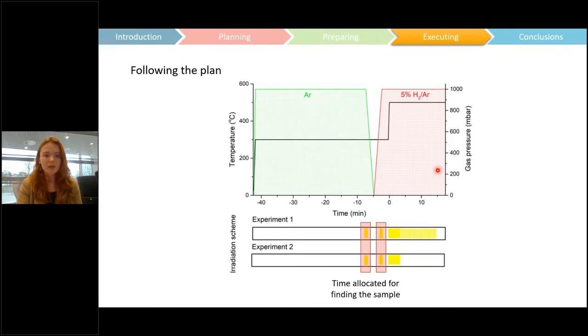And then it's just as simple as following your plan because you have a plan, you've come in with your diagram, you know what you're going to do. You have your time allocated for finding the sample. So you run your drying step. I know it's so tempting the second you get the holder in the microscope to switch the beam on and see your sample, but really hold off, run that drying step, run, I don't know, 15, 20 minutes, half an hour, get rid of that water because it really will make or break your experiment.